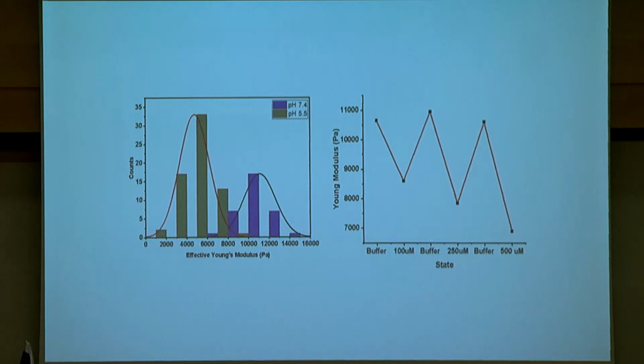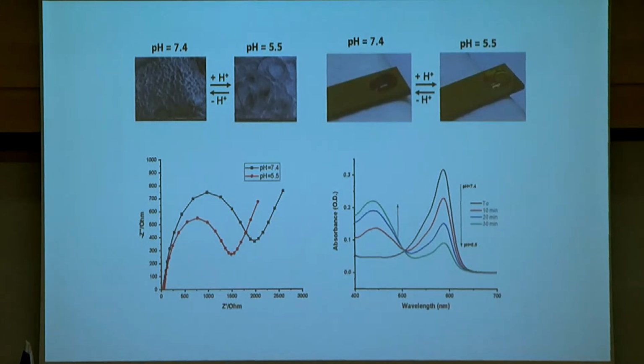First of all, the microindentation properties show you very nicely that in the presence of glucose, the stiffness of the hydrogel is controlled by the concentration of glucose. As the concentration of glucose is higher, we make a more acidic pH in our hydrogel, and the hydrogel becomes less stiff and of higher capacity and efficacy to release the insulin in the future. Now, we were able to follow these permeation properties and pH changes in the hydrogel, either by impedance spectroscopy or by color changes of the hydrogel.